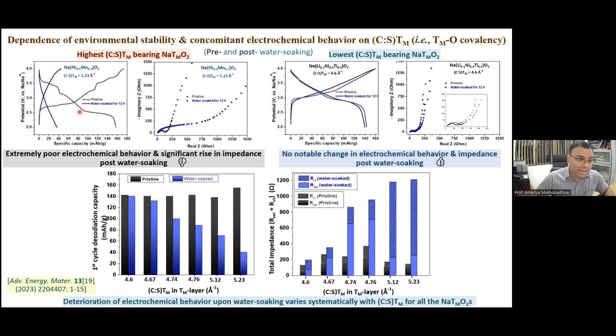Coming to the capacity, as I've shown, the capacity drops drastically for the unstable materials, as one can see here, and it is absolutely invariant even after water soaking for the water stable material having the lowest charge to size ratio, and the materials having intermediate charge to size ratio vary accordingly.